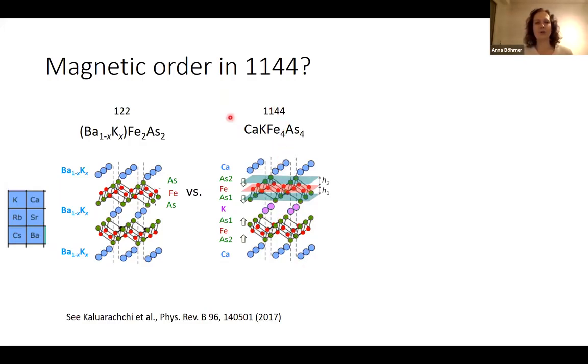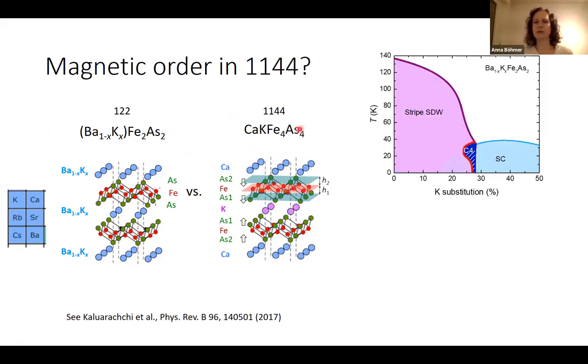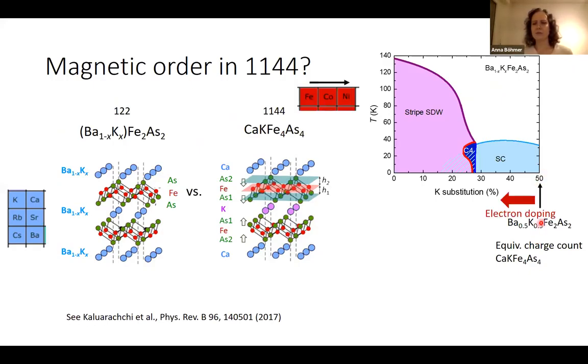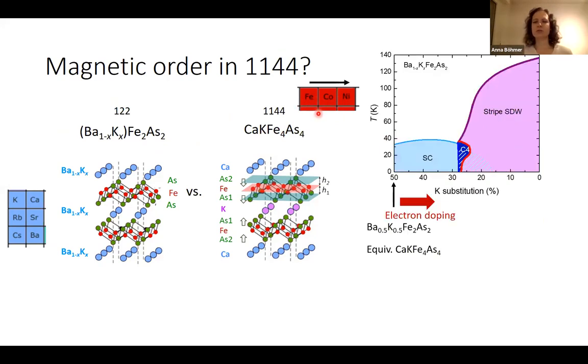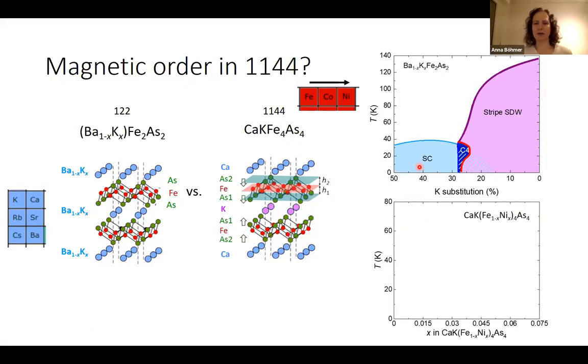If we want to know how to get magnetic order out of these magnetic fluctuations, we went back to this analogy. I show you here a phase diagram of the hole-doped 1-2-2. We are here on the right-hand side. By charge count, we are equivalent to the 50-50. If we want to go towards magnetic order, we need to reverse, we need to electron dope. We can achieve that by substituting with, say, cobalt or nickel for the iron. So to do that, let me just plot this inverse and put the phase diagram. What I will talk about today is the nickel substituted calcium potassium iron 4 arsenic 4.